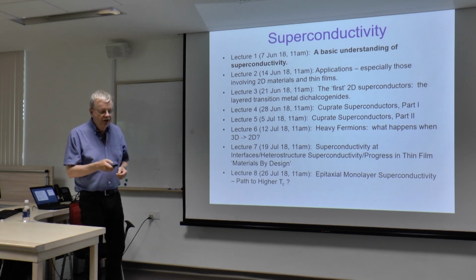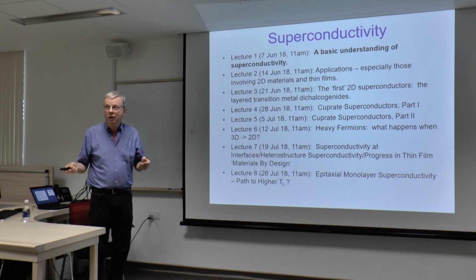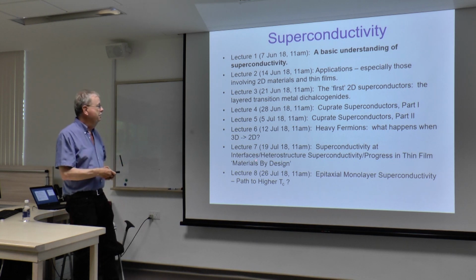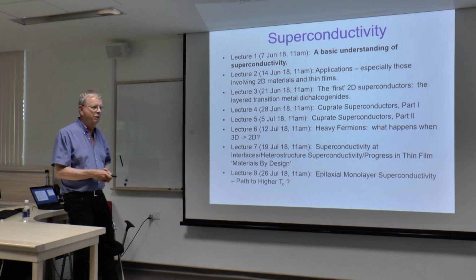In this short series of 8 lectures, we're going to talk about monolayer superconductivity. There's currently an 8-degree superconductor, which when it's put on strontium titanate goes up to around 100 Kelvin in its transition temperature. So we'll get to that.